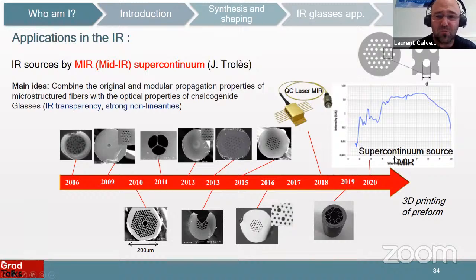As you can see, just by using light in the infrared, they are able to make a supercontinuum source in the mid-infrared range, which means by using light from 6 to 8 microns, they've developed a source with light from 2 to about 10 microns. And so how did they develop that?